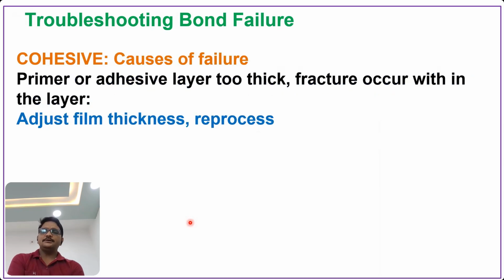The cause of cohesive failure is primer or adhesive application where the DFT is too thick, meaning the dry film thickness is higher than 35 to 40 micron, like 50 to 60 micron. If they observe that, then this failure may occur. For this, we need to adjust the film thickness and reprocess the metal.